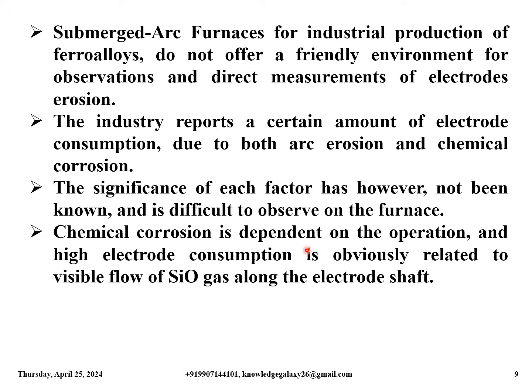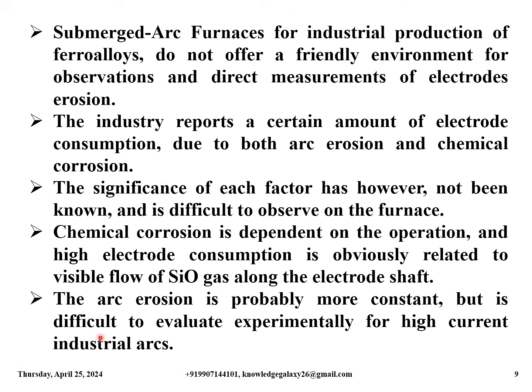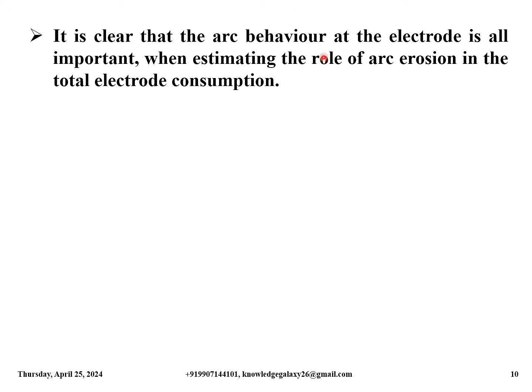Chemical corrosion is dependent on the operation, and high electrode consumption is obviously related to visible flow of SiO gas along the electrode shaft. The arc erosion is probably more constant but is difficult to evaluate experimentally for high current industrial arcs. It is clear that the arc behavior at the electrode is all important when estimating the role of arc erosion in the total electrode consumption.